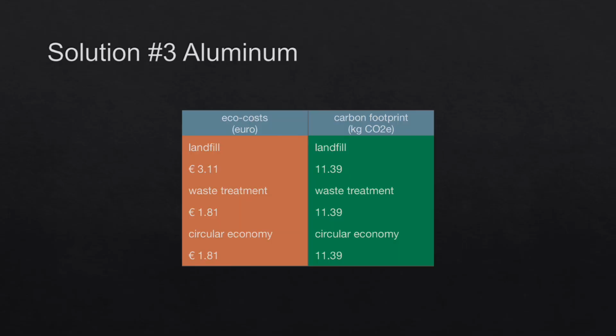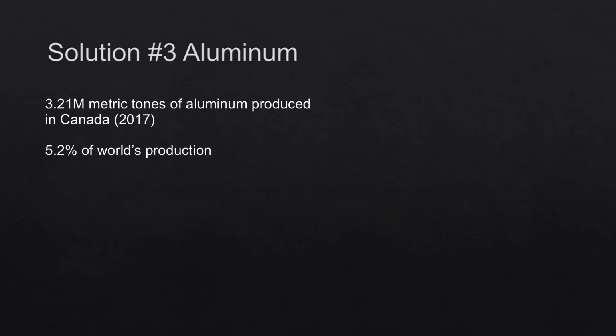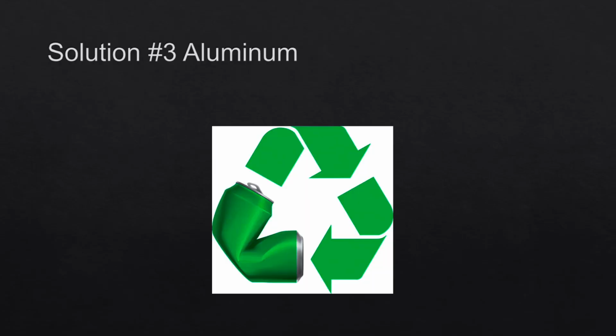Although aluminum production generates roughly 2 to 3 times more carbon dioxide than the steels, its life cycle carbon footprint is considerably less at 11.39 kilograms of carbon dioxide emissions. A part of this can be attributed to its large domestic production in North America, which reduces transportation emissions, and aluminum being 100% recyclable, meaning that it retains all of its material properties one cycle after another.